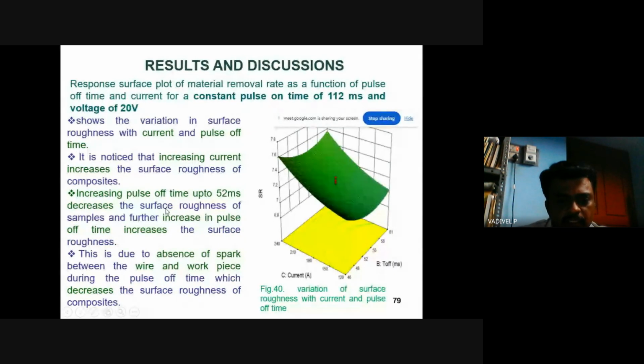Here is the graph of the variation of the surface roughness with the current and the pulse off time. Increasing the pulse off time up to 52 milliseconds decreases the surface roughness of the sample, and a further increase in pulse off time increases the surface roughness. This is due to the absence of spark between the wire and the workpiece during the pulse off time, which decreases the surface roughness.